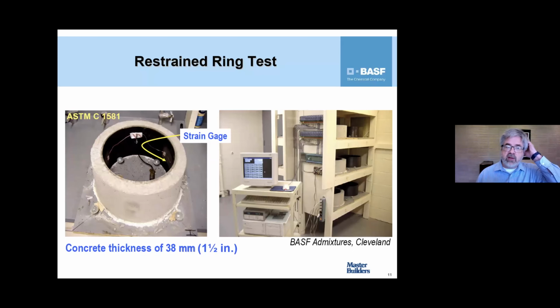We also have done some work with the restrained ring test. Actually, a lot of this work is still underway. This is a somewhat recent test where we cast concrete around a steel ring and then we put strain gauges on the inside of the steel. If you've not seen this test before, the first instinct is to be skeptical. You mean the concrete shrinking around the ring is going to be actually measurable on a big, thick piece of steel like that? The answer is yes.